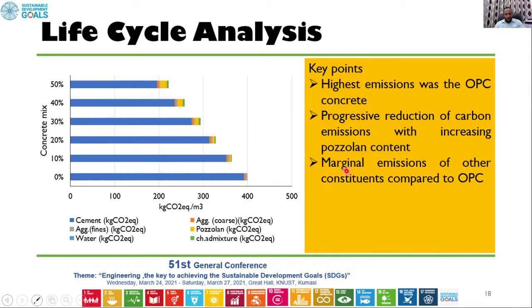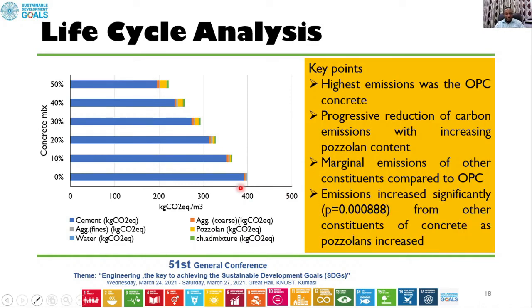Again, there was also marginal emission of other constituents compared to OPC. So the other constituents, that is coarse aggregate, fine aggregate, and water, the differences weren't that much. The difference between the OPC and the other constituents was not that much. So you can see compared to the OPC. And then as the pozzolan also increased, the carbon content of the other constituents was also increasing. So you see, it started very low, then here it was increasing, here it was increasing, as pozzolan content was also increasing.